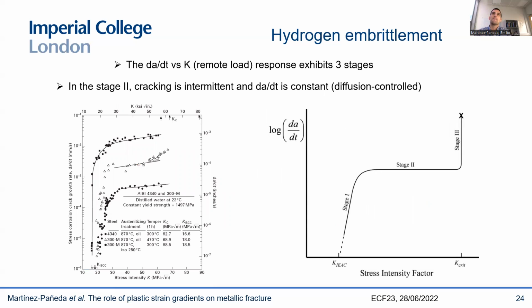The other reason is that the critical distance for hydrogen embrittlement is 1 micron ahead of the crack tip or less, or around that number, basically. And you can get that from experiments, because in hydrogen embrittlement, you basically see this 3-stage regime whenever you plot crack velocity versus stress intensity factor. So you have a cracking threshold, you have a stage 1 where the crack speed grows significantly with the loading rate, but then you have this stage 2 where no matter how much you increase your stress intensity factor, your crack speed remains the same. And the reason why this happens is that this is a diffusion-dominated regime, basically.